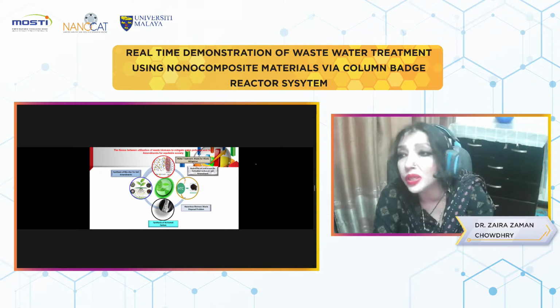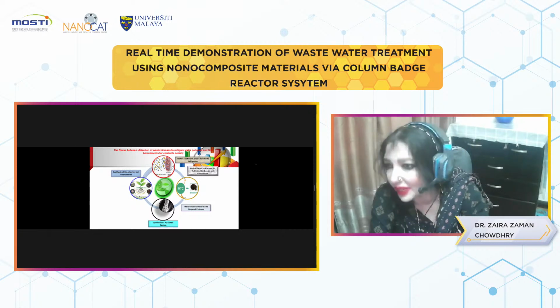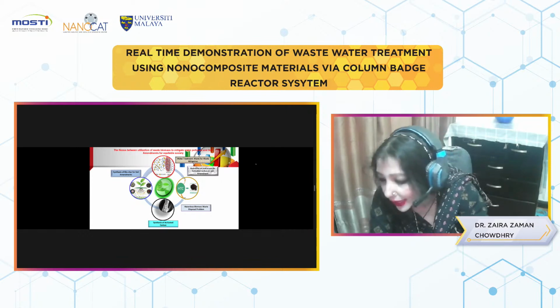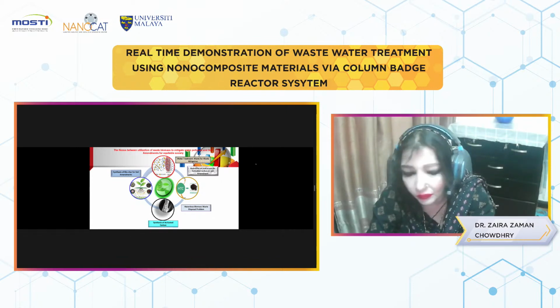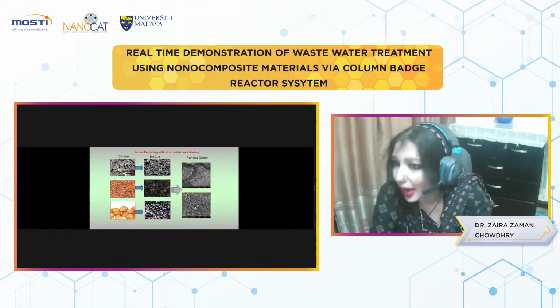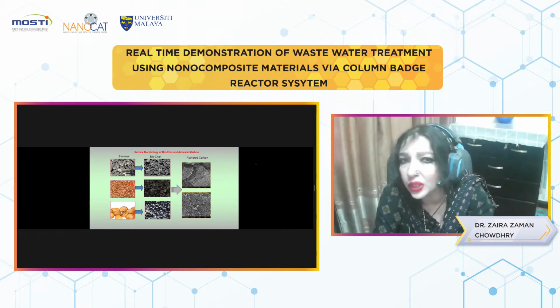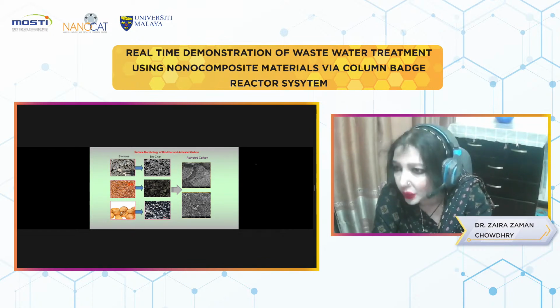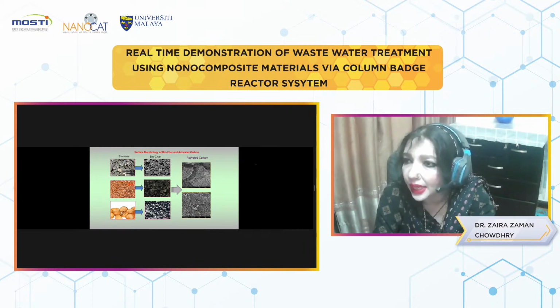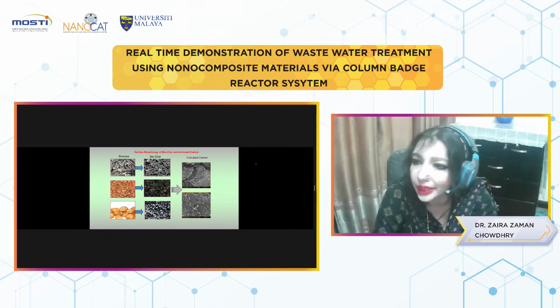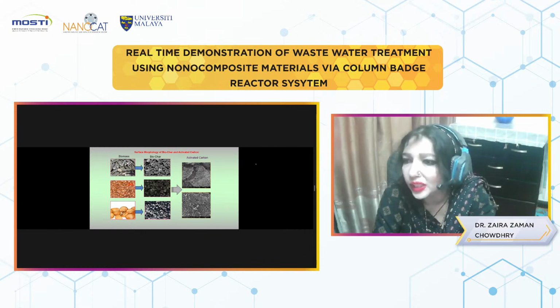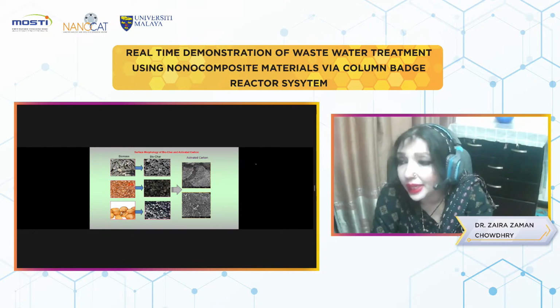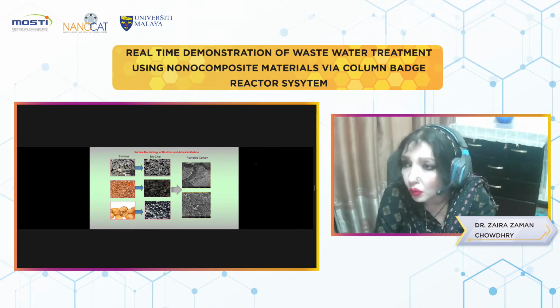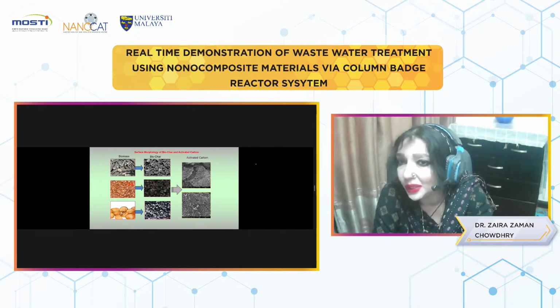Why we activate biochar and hydrochar? To have more surface area. We can use a small amount and we can remove lot of pollutant. That's why we use like this way, right? This is some common types of biomass. In here, we have used two steps, right? First, we have converted it to biochar around 400 degrees centigrade. When we activate the carbon, the surface became porous like this. We can see right side, in my right side FESEM picture, we can see that it is porous. So these pores are going to collect the heavy metals or the dye pollutant, just like a sponge. We can remember, just like a sponge we use in our home for cleaning, activated carbon surface is just like a sponge. Okay.